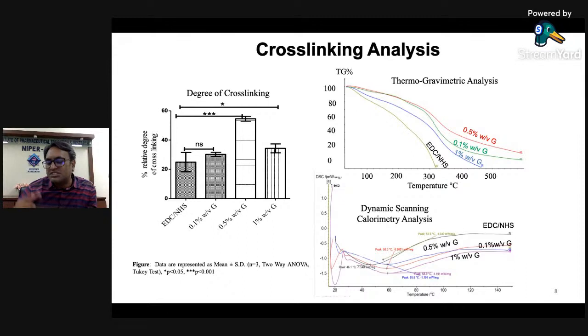We have further checked the cross-linking of our material with graphene and collagen by thermogravimetric analysis and differential scanning calorimetric analysis. The 0.5% shows much more stability compared to the other concentrations of graphene, which further shows that this material has high cross-linking, and that's why probably it is more stable to temperature.